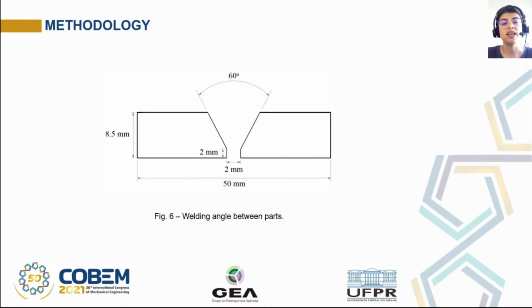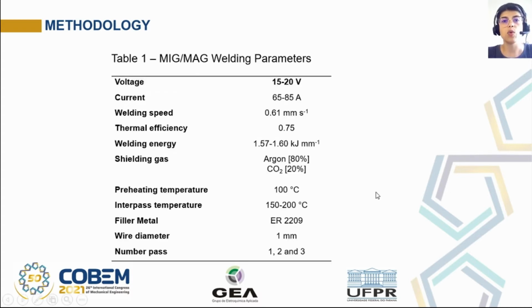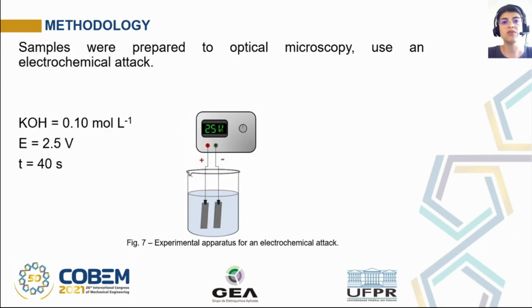In our methodology, we used beveled pieces and the angle between these parts was 60 degrees. The dimensions of the pieces are shown in Figure 6. Table 1 shows the parameters used in our welding experiments. The voltage used was from 15 to 20 volts, the current used was from 65 to 85 amperes, and the number of passes used was 1, 2, and 3. After the welding process, samples were prepared for optical microscopy, and for this we used an electrochemical attack.